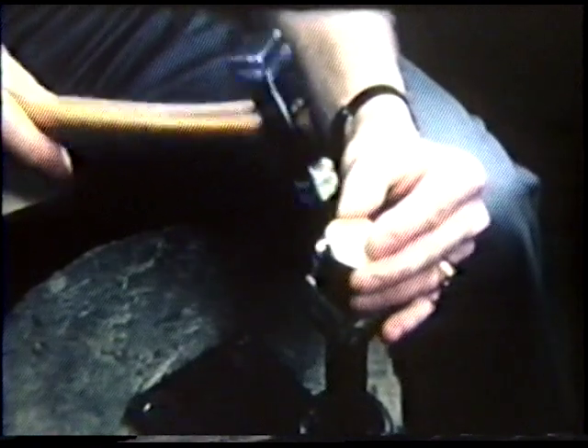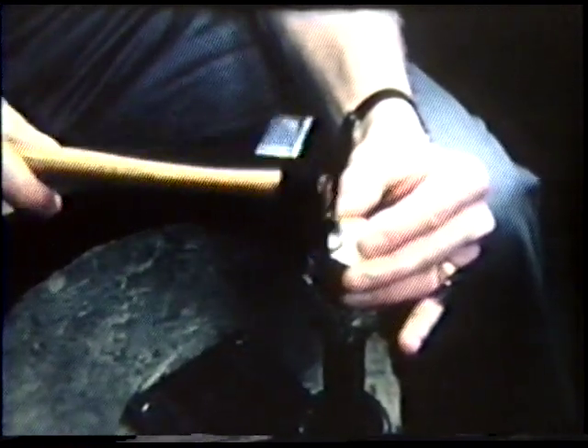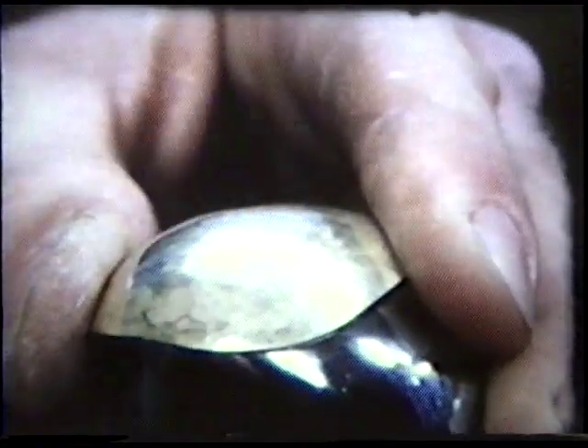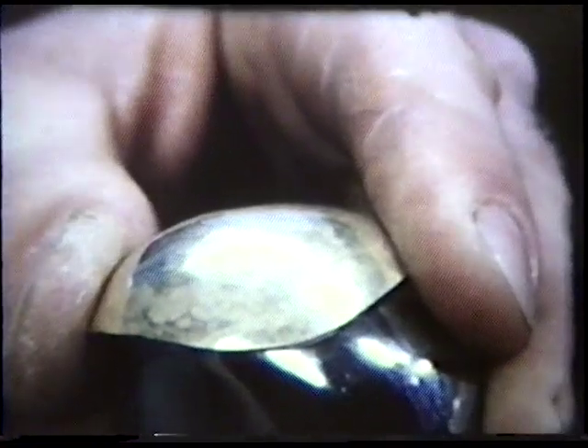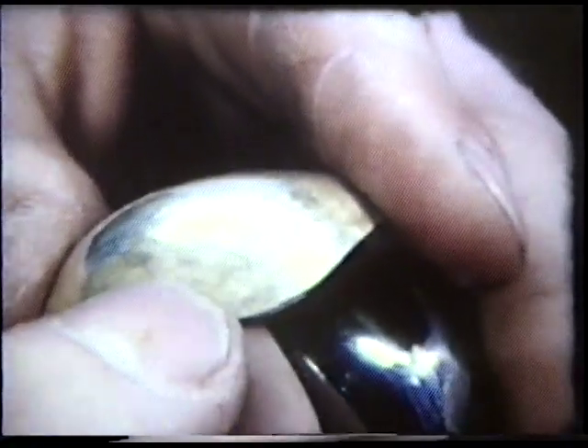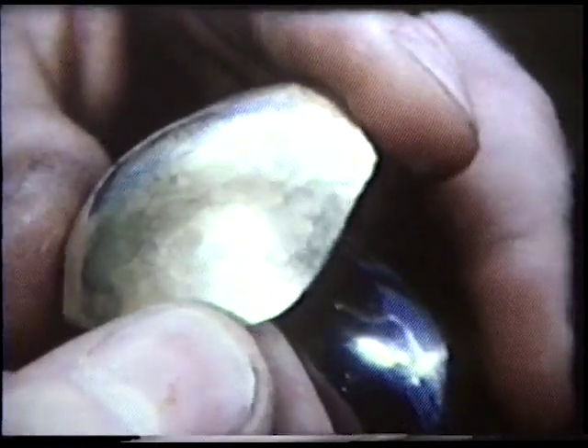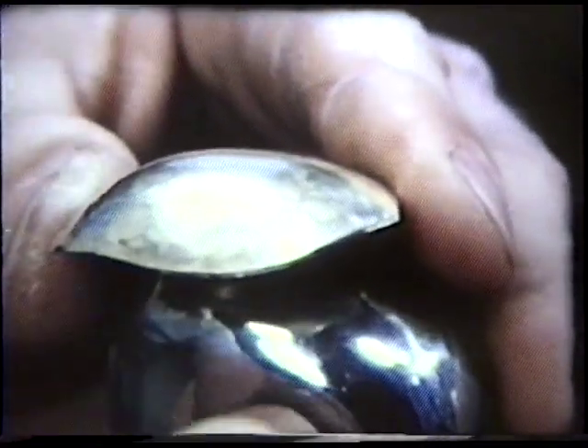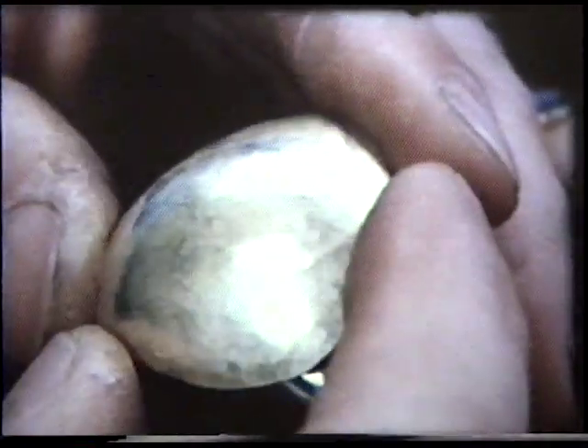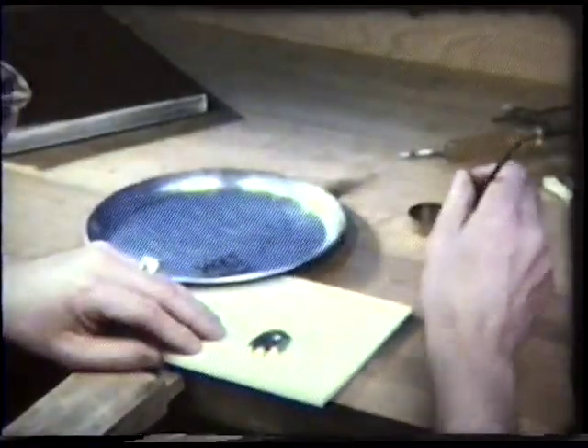A highly polished steel form called a stake is selected, which will fit the general form of the back. Light blows of the planishing hammer develop the subtleties of the form and remove the marks left by the heavier forming hammer. The blows work out from the center in concentric circles until the entire surface has been covered. Planishing allows the craftsman to refine the form and develop its subtleties. When this process has been completed, the piece requires only slight buffing to polish it.